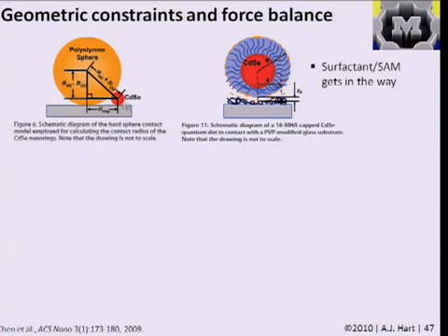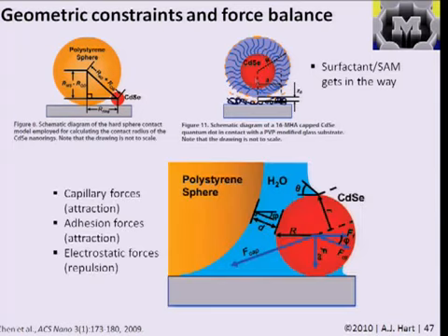And the paper talks about how the geometry, the size of the quantum dot, and its size in proximity to the particle, for example, thickness of the organic coating, the monolayer and/or surfactant that's assembled on the particle plays a role, as well as the balance of forces in this situation. For example, as we saw today, you have capillary forces that draw the particles together, and you also have adhesion forces between the nanoparticle and the substrate, and between the nanoparticle and the microparticle. And also there are double layer forces, electrostatic repulsion, that cause the particles to want to repel each other. So it's effectively a balance of these forces, or the forces being forced in a certain regime that facilitates organized assembly by this template. And you can imagine that the influence of these different forces is much different on a nanoparticle than it is on a microparticle, and that also plays an important role in these types of assemblies.